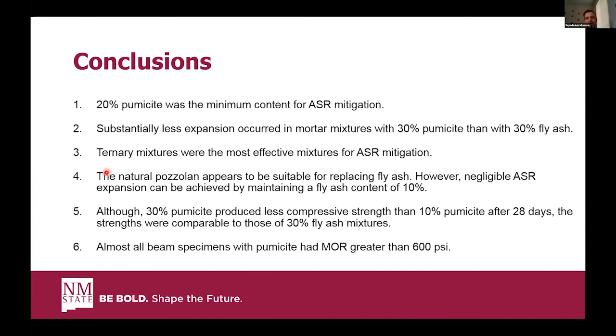For the compressive test, we found that with increasing the pumicite, the compressive strength decreased, but mixtures with 30% pumicite had really close compressive strength to the mixtures with 30% fly ash. So we can suggest that pumicite can be a good alternative to fly ash again. In the flexure test, we found that almost all mixtures, other than just one of them, which was the mixture with 30% fly ash, had an MOR greater than 600 psi, which is again acceptable to many transportation agencies.